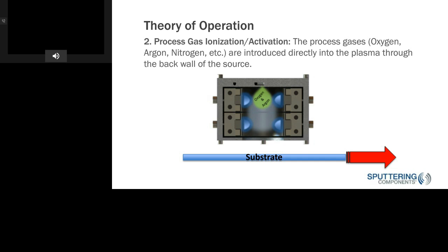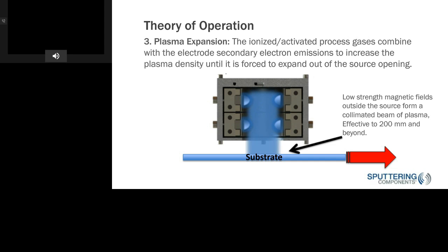And finally, for the plasma expansion, the ionized or activated process gases combine with the electrode secondary electron emissions to increase that plasma density in the cavity until it's forced to expand out of that opening. And then we also have low strength magnetic fields to produce this collimated beam of plasma. And we typically see that we can have a source to substrate distance up to 200 millimeters to get effective treatment.